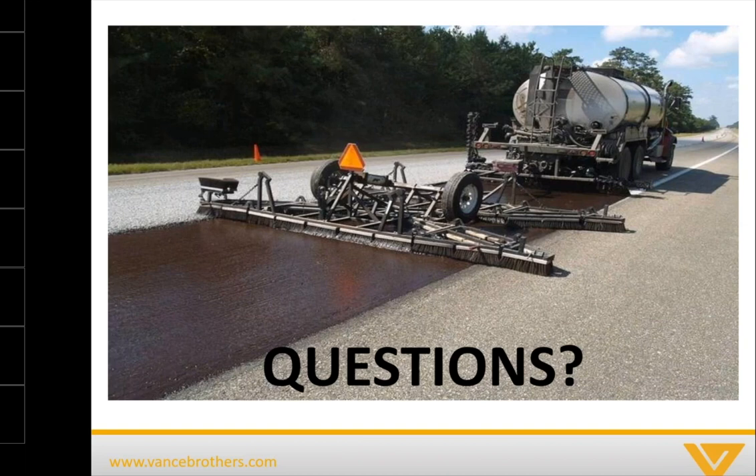Wes, if you're still on, I got an answer from Sean Brost via text — he typically sees eight pounds per square yard of aggregate. Hopefully that gives you an answer. Cody Thompson asked what the difference is between a fog coat and a micro seal. That would probably be a whole different presentation, but a fog seal is really just a thin layer of sprayed-on emulsion, doesn't add any structural integrity, and doesn't have any aggregate in it. Microsurfacing is laid down differently — you have actual aggregate rocks in it — so there's a significant difference.